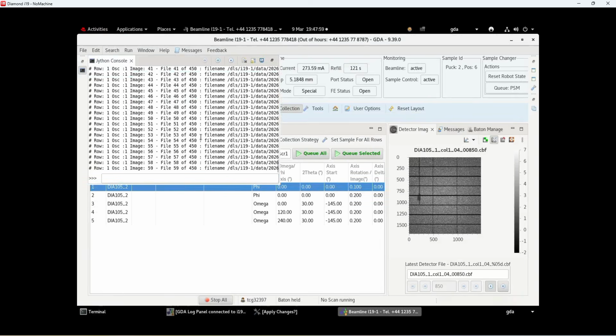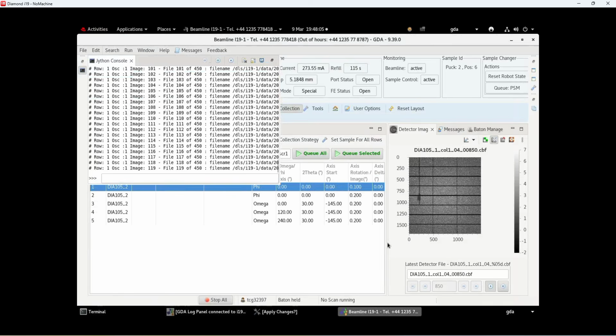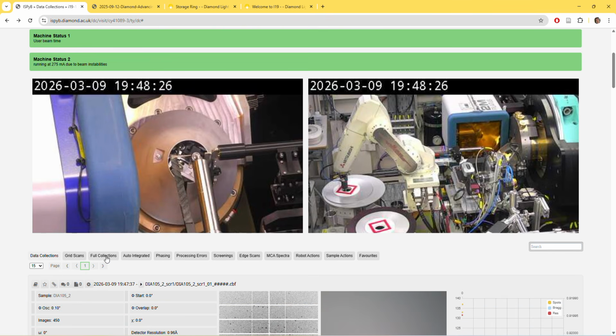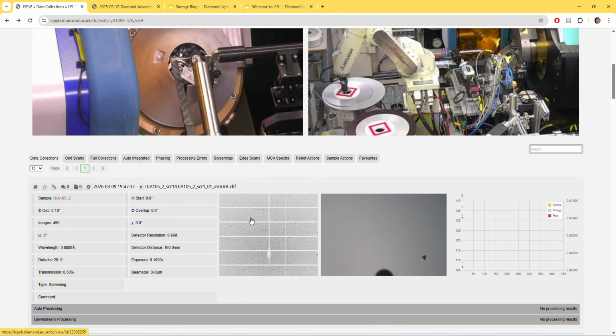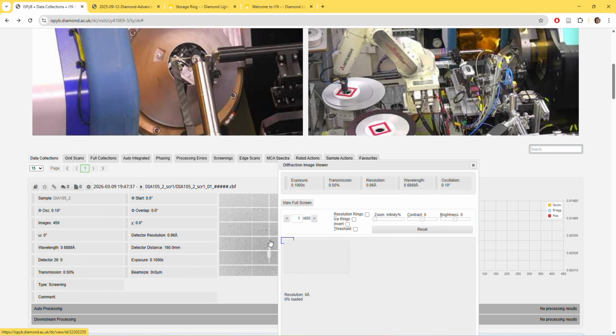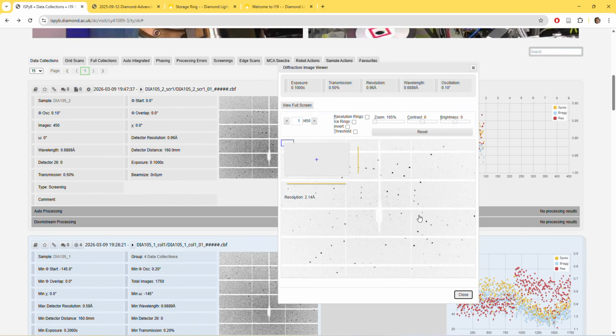You could view it in a viewer, but we should be able to see some sort of diffraction image here as well. It won't be of very good quality, but we could do that. The problem is that you don't want to open thousands of windows during this beam time. We have about 100 crystals to measure, so I don't really want to waste time for that. And we should also see it in our processing website. That's the old crystal, I think. No, that's the crystal. So you can see that the diffraction pattern is nice, strong. We can see nice diffraction spots. So yeah, looks pretty good.